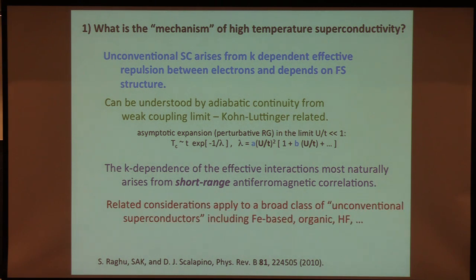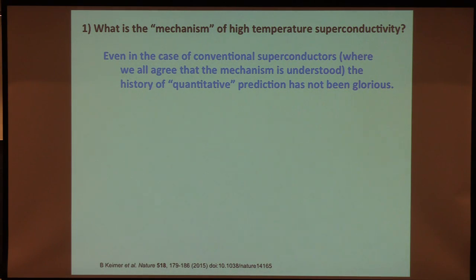So, yeah, the basic answer is that this is an electronic mechanism. Exactly. And so the prefactor is bigger, and after all, if you look at how you get anomalously high TC from a phonon mechanism, it's not by making lambda bigger. Lambda is always 1 in all of the decent electron-phonon superconductors. The ones that have the high transition temperatures are magnesium diboride and hydrogen sulfide under pressure, all things where the phonon frequency is much bigger. So making the prefactor bigger isn't an insignificant idea.